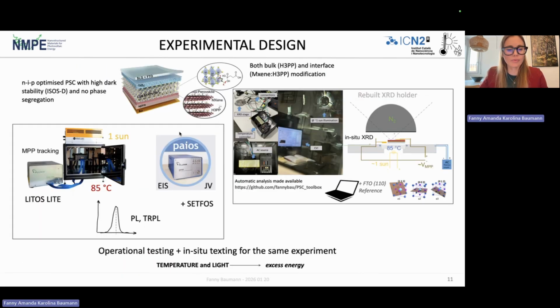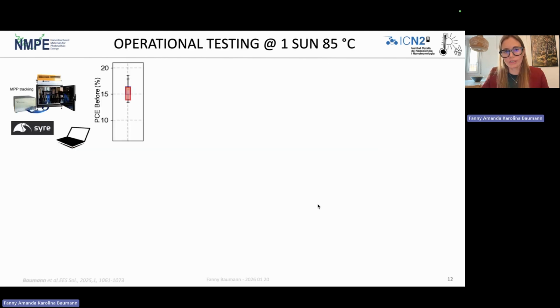And just to summarize the methods, we are going to use then Litos Lite operational stability test together with Paios impedance spectroscopy measurements and JV. We're also going to do photoluminescence and time resolved photoluminescence and some simulation in SETFOS. Then we have our in-situ in-operando X-ray diffraction setup with similar conditions. Some automated analysis, and also I want to say that we did also impedance spectroscopy and photoluminescence analysis before and after these XRD tests, but to a lesser extent, and these were made to ensure that we have a very similar situation both before and after the test. So again, I want to just remind you that we're using temperature and light, so we're adding a lot of excess energy. And now we're going to start looking at the results.